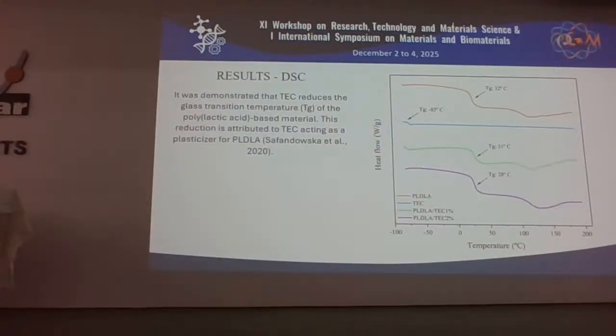DSC: it was demonstrated that TEC reduces the glass transition temperature of the polylactic acid materials. This reduction is attributed to TEC acting as a plasticizer of the PLDLA.